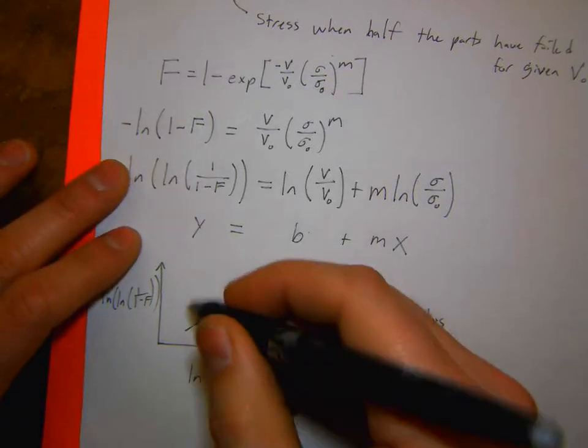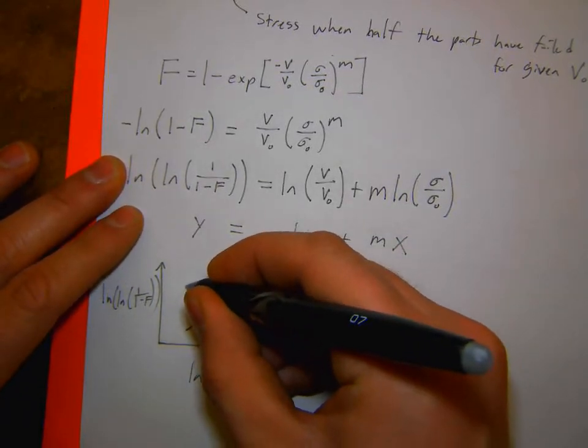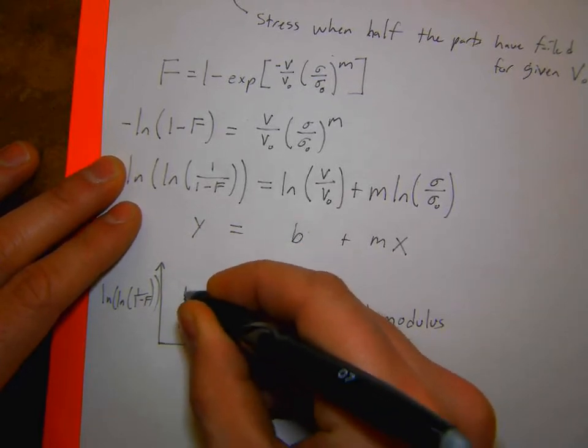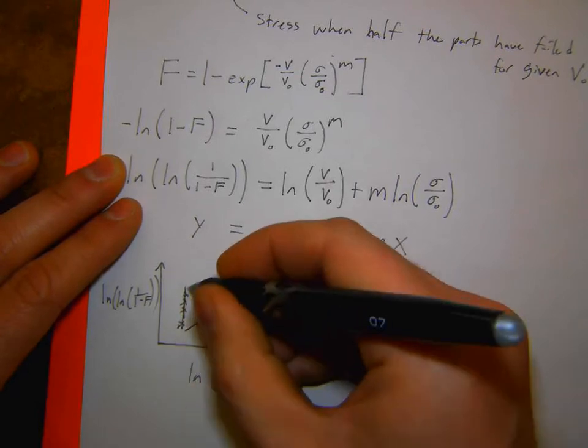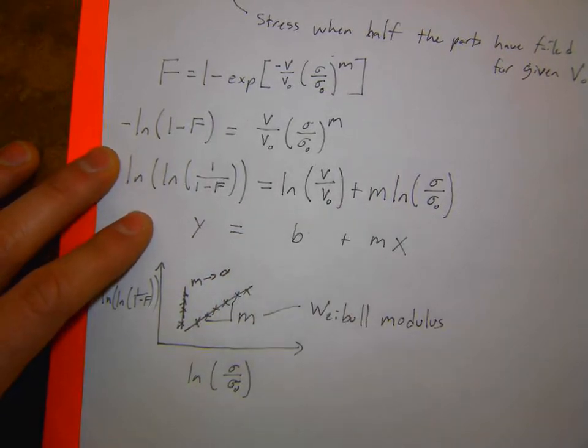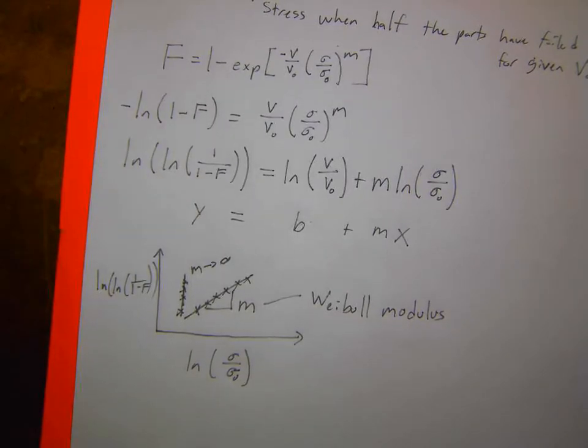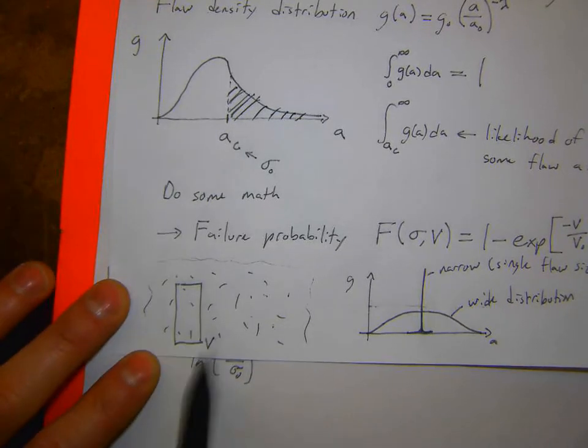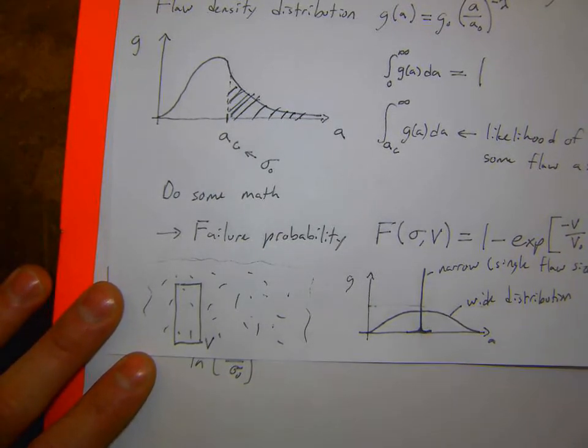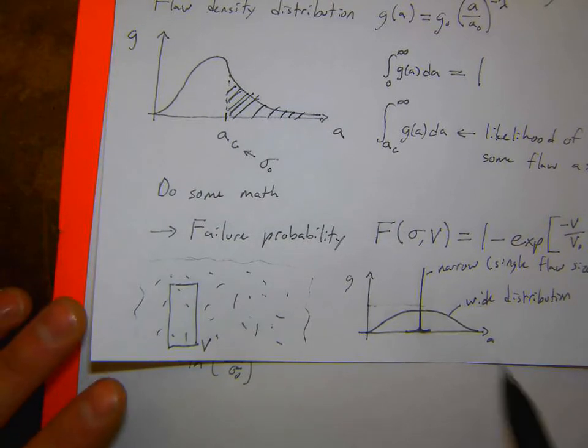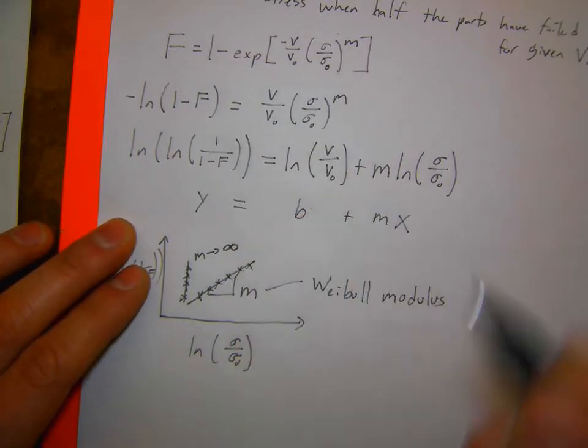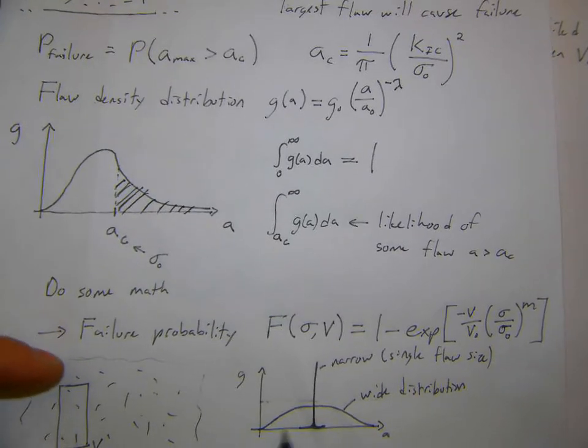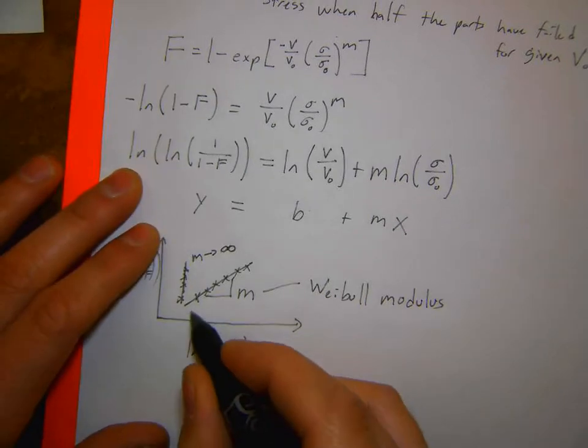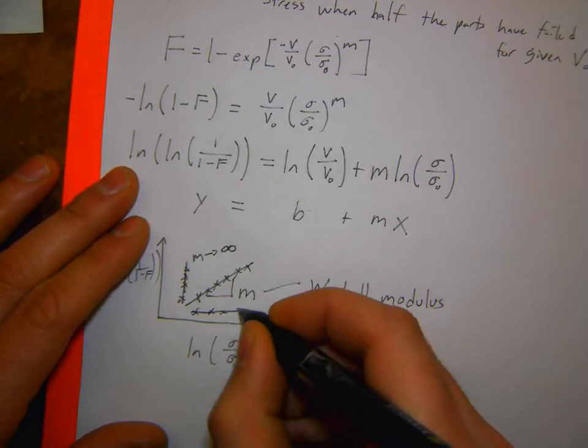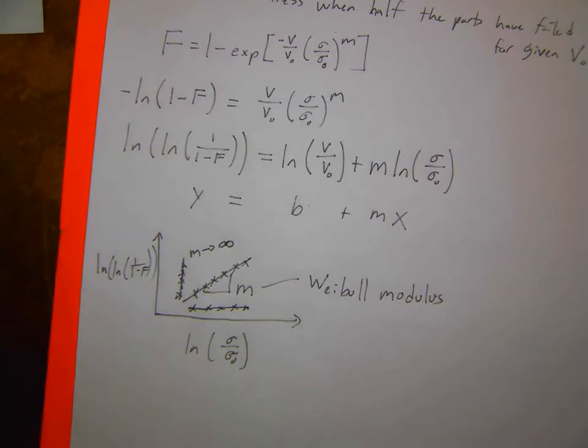So if I have a very large m, if I have one stress that these things fail at, as my m goes to some very large number, that means I have exactly one flaw size. So if in my random distribution of flaws, I have that one critical flaw size, that one A that exists everywhere in the thing, that's going to be where failure happens all the time. And so I'll get something that's almost straight up and down. This is an infinity. But if I have an incredibly wide distribution, if I don't know what my distribution of flaws is, I could have an M that's very low, and my part could fail randomly at any applied stress.